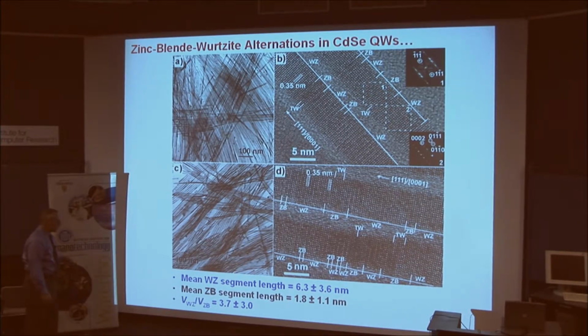And here I show on this slide the main kind of defect characteristics found in the wire. These are high resolution images, and if you have a sharp eye, which my postdoc does, you can look at this and assign regions to their various crystal structures. So cadmium selenide we would normally expect to exhibit the wurtzite structure, but what we can see is that there are regions in this wire that are wurtzite, and they're interrupted by domains that are zinc blende, and then wurtzite and zinc blende, and so on. In these cadmium selenide wires, the mean segment length for a wurtzite segment is about 6.3 nanometers. The zinc blende mean segment length is about 1.8, which means that the volume ratio in the wires is about 3.7 to 1 for wurtzite to zinc blende.